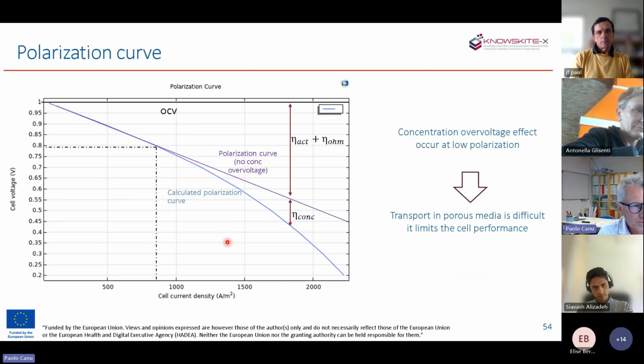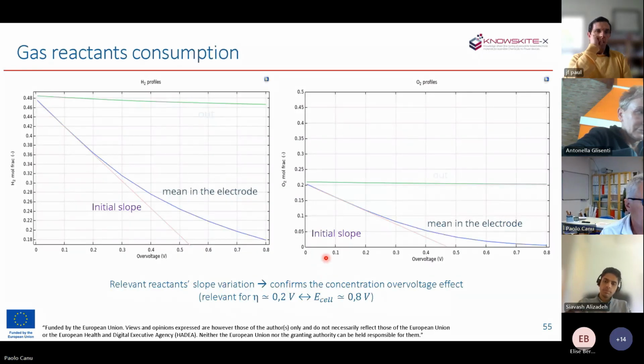The model is also able to predict the polarization curve starting from the open circuit voltage. We can identify all the overvoltages due to concentration, activation, and ohmic. And the prediction is the blue line, and that is immediately comparable to experimental measurements.